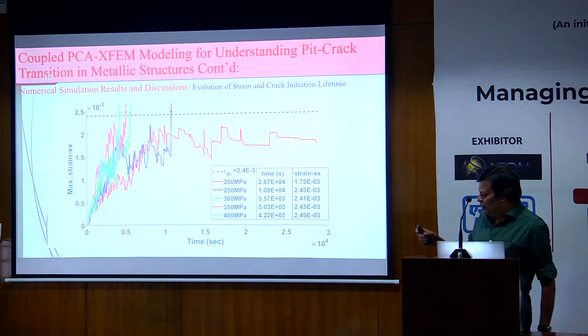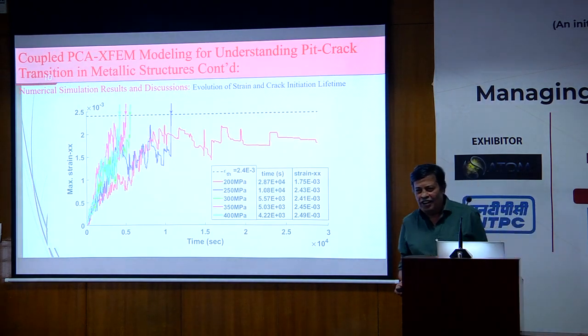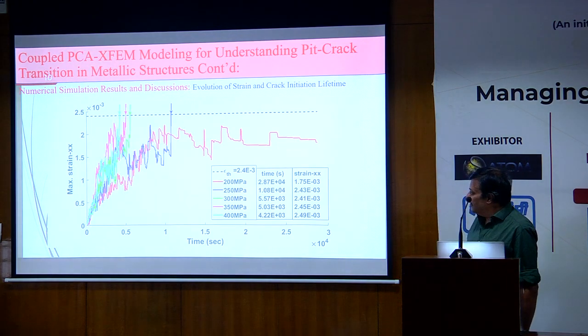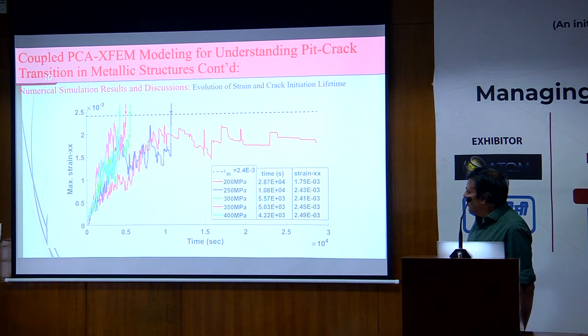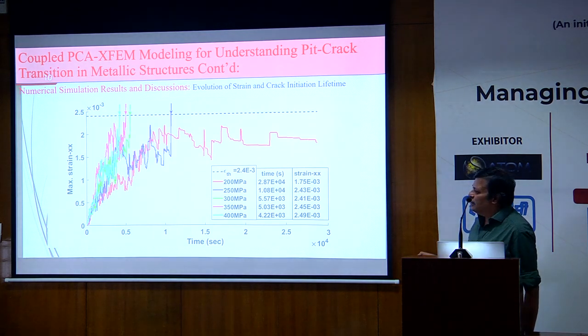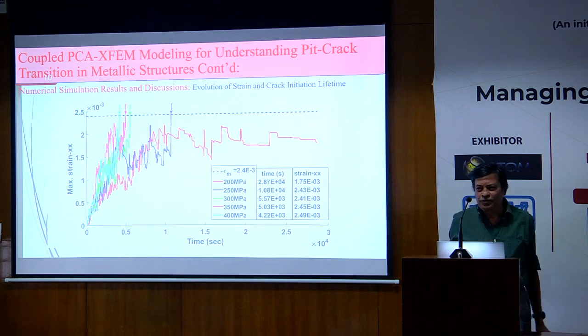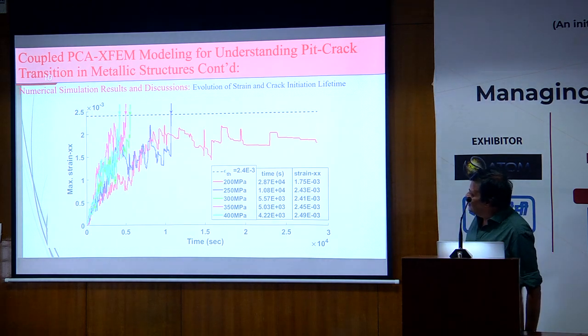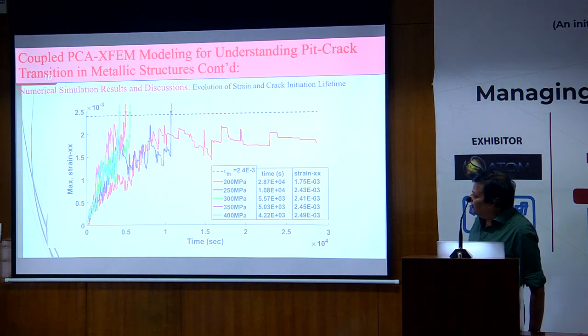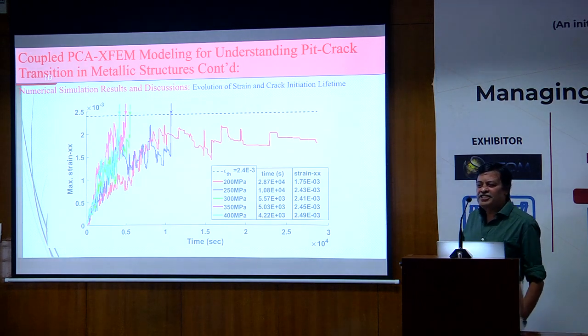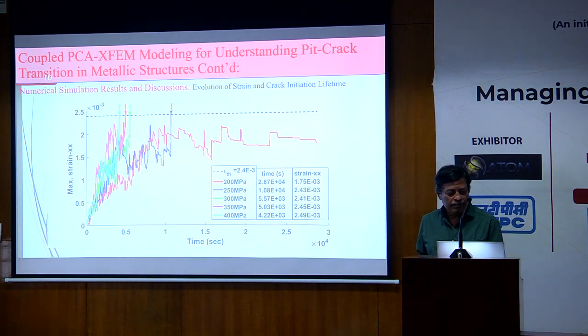So this is a result which Bob did not show. I am showing it. This is under different stress levels. What happens? You see that when the stress level you apply to the metal side is 200 MPa, the threshold strain will not happen. That is, pit to crack transition is not an issue. But as the stress increases, you see at different times, the time at which the pit to crack transition happens is much lower. So we can easily predict this using this model.